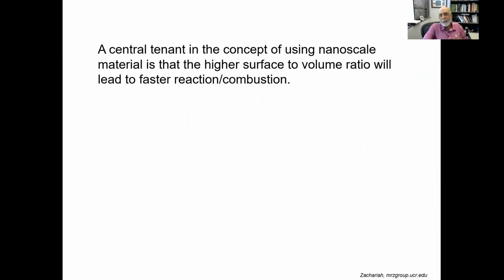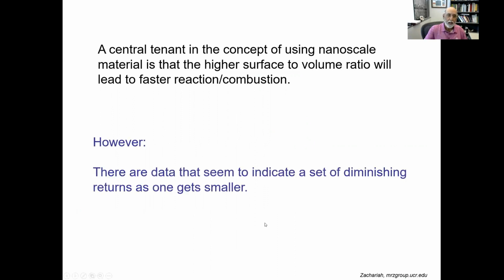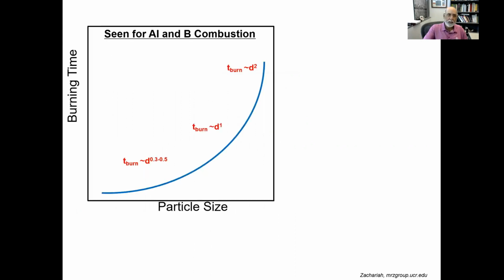So one concept that's been central to almost everything that's been done to drive the idea of using nanoscale materials is that high surface area to volume ratio leads to faster reactions in combustion. But the reality is it doesn't seem to work quite as well as we'd like. So this is a conceptual plot. Actually, the plot was first made by Rich Yetter, and I'm adapting it for a different purpose. But this is burn time versus particle size, and there's lots and lots of data, and this plot just conceptualizes what you see, that there's a high sensitivity for particle size when the particles are large.